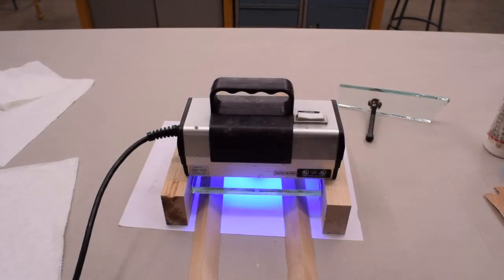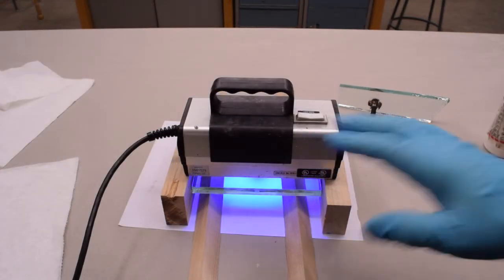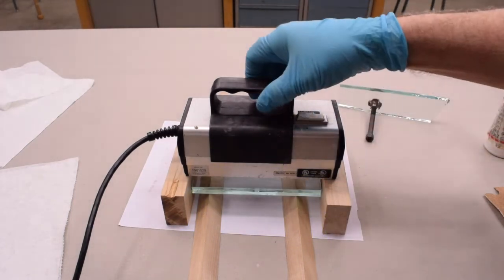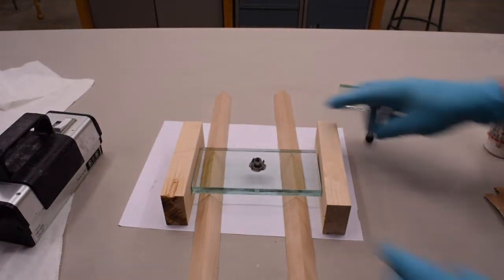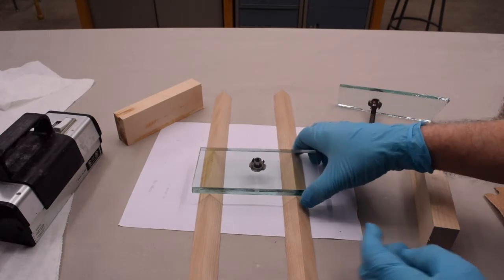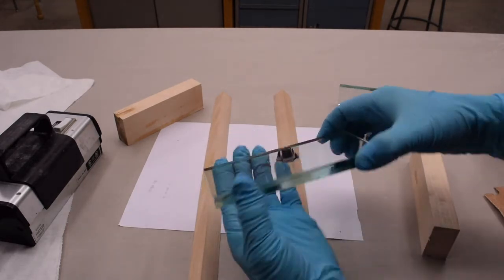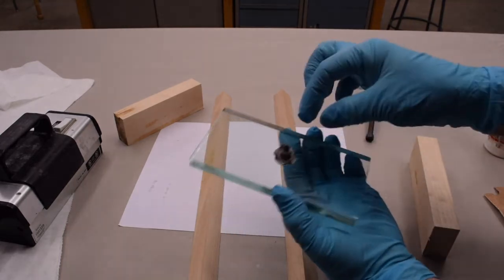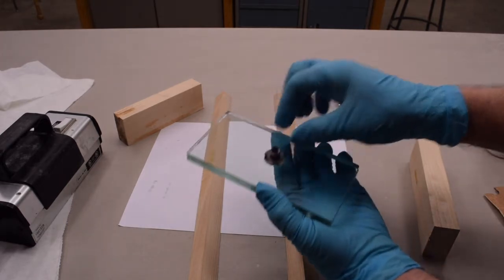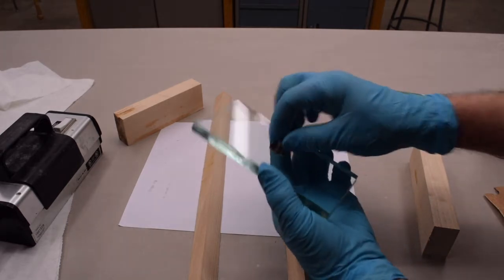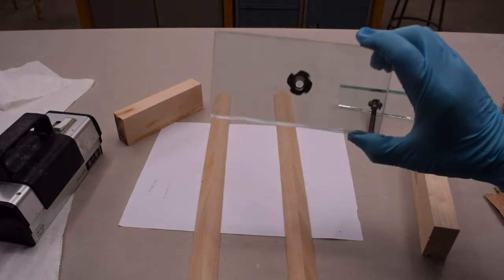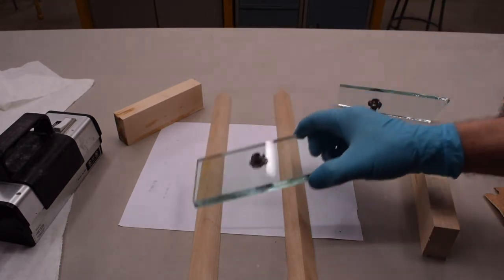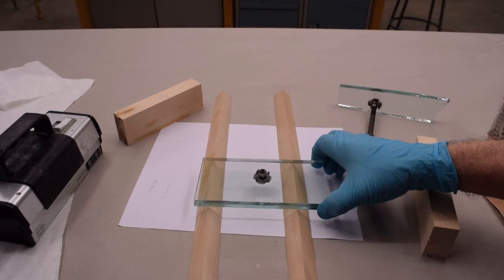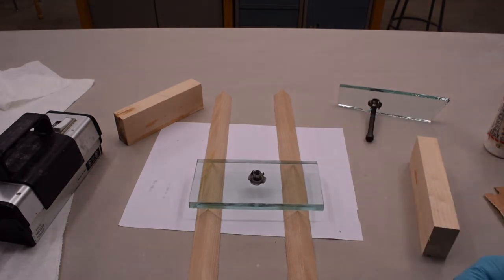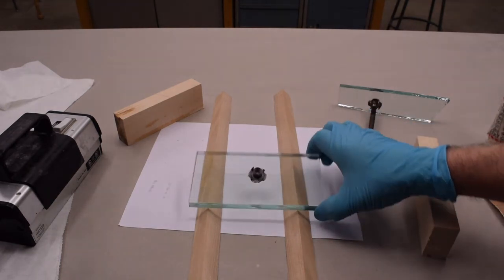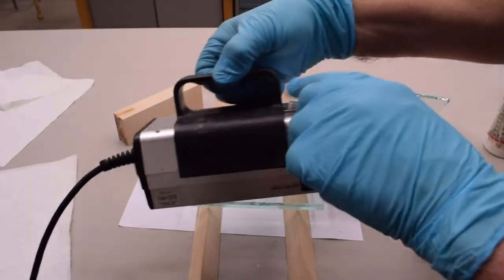So I've left this light on for about 10 minutes on our assembly, so I'm going to turn the light off and we'll see how it has cured. Let's move those blocks away. Glass is not shifting, and that little metal stud, the T-nut, is adhered quite securely, and it's nice and clear. So it's obviously done its job, and that's how you glue glass together with a UV curing glue and the UV light.